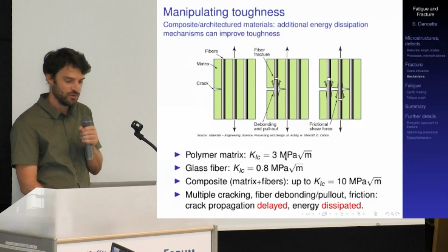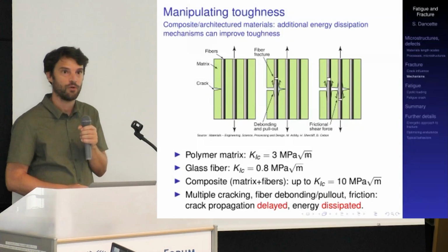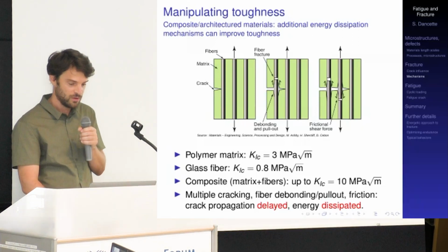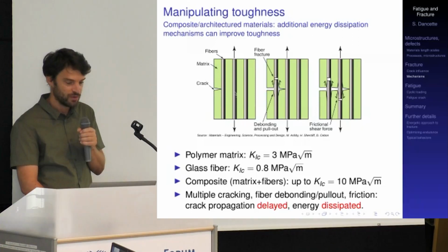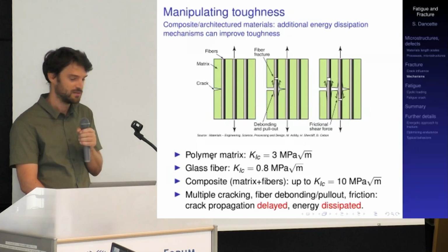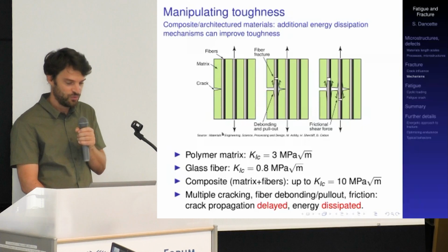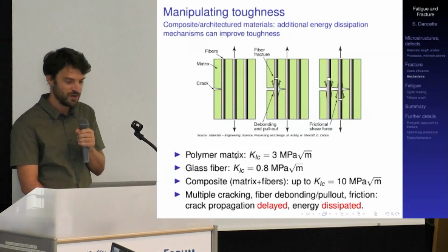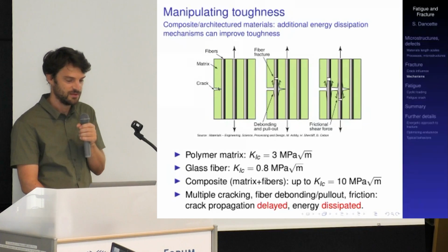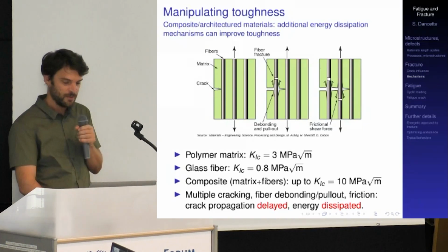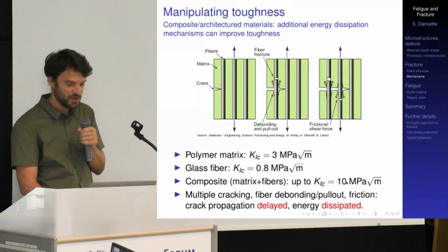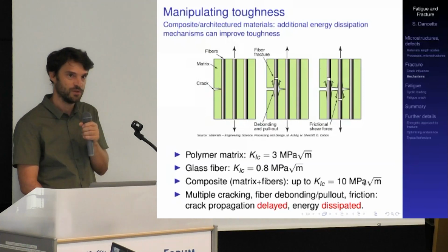So 3 megapascal square root meter is rather low for fracture toughness compared to metals, for example. The glass fiber itself is very strong and very stiff, but also very, very brittle. So even less than the polymer matrix. So less than 1 megapascal square root meter. You can see here that when you elaborate a composite material with the matrix plus the fibers, due to the arrangement of the fibers and its interplay, let's say, with the matrix, the fracture toughness of the composite material can range up to 10 megapascal square root meters.